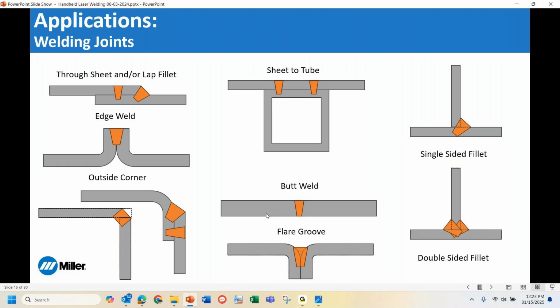A lot of manufacturing for conventional welding processes might have gaps or might have edge prep like a bevel put onto a component, because we're adding a significant amount of filler metal to those parts with conventional welding, whereas with laser we're more trying to use the substrate of the original base material in order to provide the strength to our weldment.